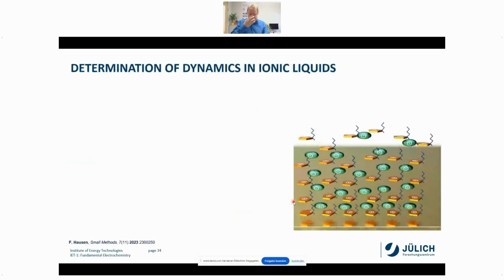As a last aspect, I would like to show in the remaining couple of minutes that we cannot look just at the interfaces and study, let's say, the chemistry of these interfaces, but we can also follow the dynamics of our materials, in this case an ionic liquid. Ionic liquids have the specialty that they form these nice layers. So if you have a gold surface or any other metallic surface which is really smooth and you apply a certain voltage, then ionic liquids form a number of layers on top of the surface, and then the tip penetrates through these layers, and then you can see this interfacial layer of the ionic liquid in front of the electrode.